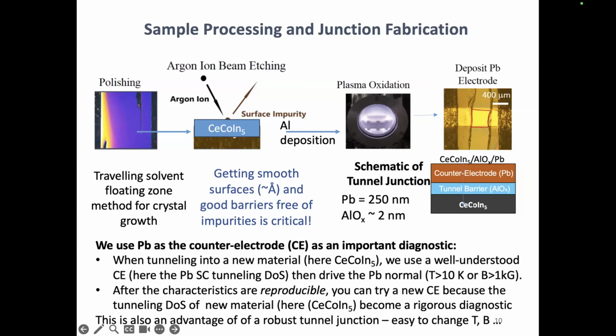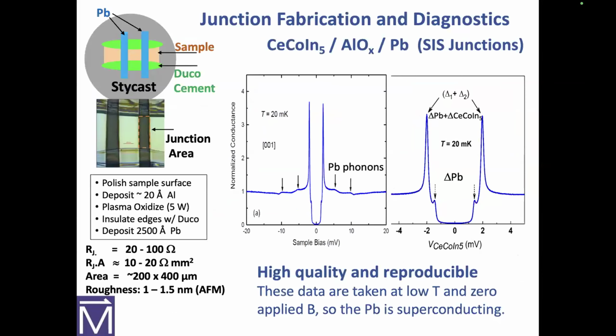After we do enough of this work, we get a feel for what the CeCoIn5 tunneling conductance looks like, and then we can switch counter electrodes because we have such a good idea what the tunneling density of states looks like in CeCoIn5. That becomes no less a diagnostic as to the quality of the junction. And then whether you're looking at high Tc or this stuff, you put a little temperature on it, you put a little field on it, you drive the counter electrode normal, and then you're looking at the counter CeCoIn5. So this is just to show you the quality of the junction.